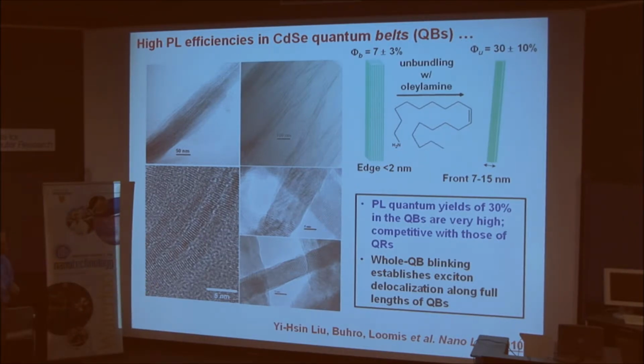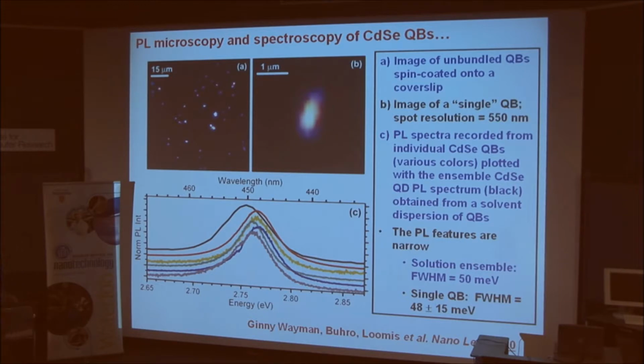Additionally, when I showed you the quantum wire blinking, I told you that only 2% of the wires exhibit that whole-wire blinking behavior. But all of the belts do. So all of the belts, by that criterion, would seem to have exciton delocalization along the entire length of the belts. These have a Wurtzite crystal structure, by the way, and we don't find any zinc blende domains in these belts. Here are some optical microscopy images of these belts. Here's a bunch of belts just showing you that all of them are bright, and you might say, wow, they don't look very much like belts, they look more like cough drops.